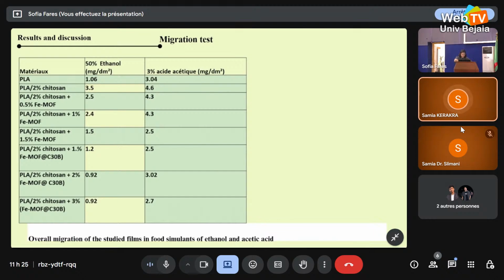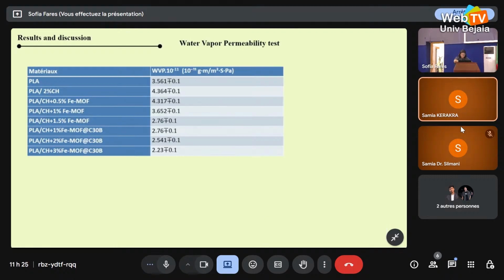Water vapor permeability test, as you can see in this table too, while chitosan increases hydrophilicity, MOF and the composite MOF clay improve the barrier properties of the composites by reducing water vapor permeability. So fillers enhance the overall structural integrity of the composite, creating a stronger and denser barrier against water vapor.